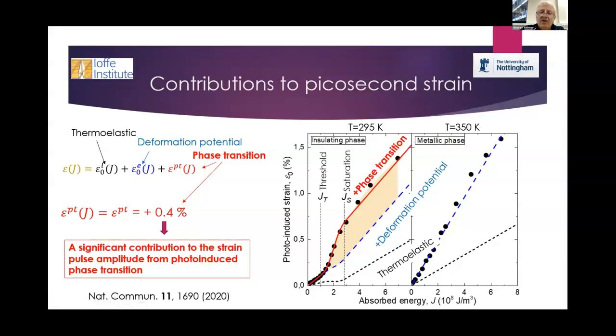It is about 0.4% of the strain. And actually the strain amplitude may be very high. It is about 1.3%. Actually in metallic phase, it is also — this material is very good.